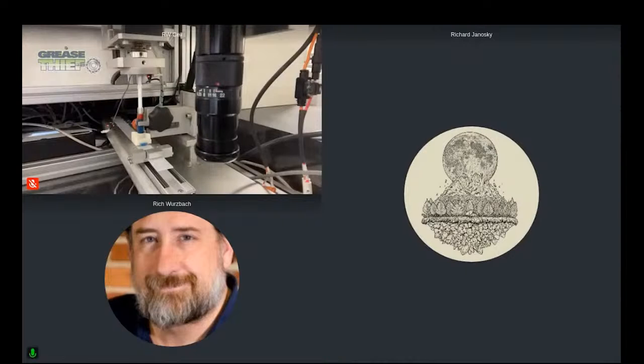Yeah, of course, in the design we created a weir feature that tends to push some of the large particles off to the side to keep them from clogging. So a certain amount of that is accounted for in the design of the flow channel. But there's a certain point at which you overwhelm that, right? And that's when we see the clog function. That is correct. But yet that's a data point in itself, isn't it? The fact that it clogs says, hey, this grease has changed significantly from its new condition. And that's certainly going to affect its behavior in that machine, the way it's able to lubricate effectively, move around within that environment, even its ability to be displaced when new grease is being pumped in.